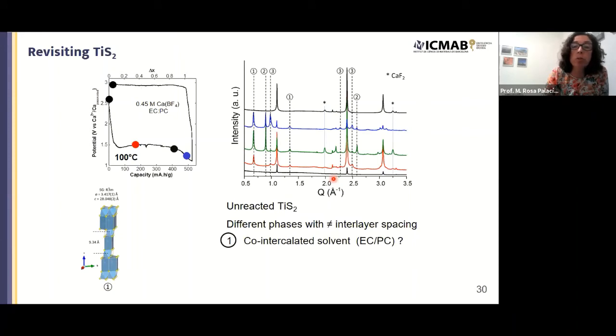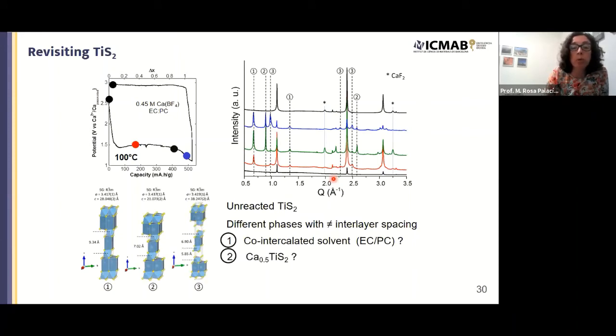Those are the three phases that we were finding. The first one has a very huge interlayer distance, and we believe that it corresponds to calcium intercalated together with some solvent molecules. The second one seems to have the same cell parameters as reported by Jean Rouxel for Ca0.5TiS2.